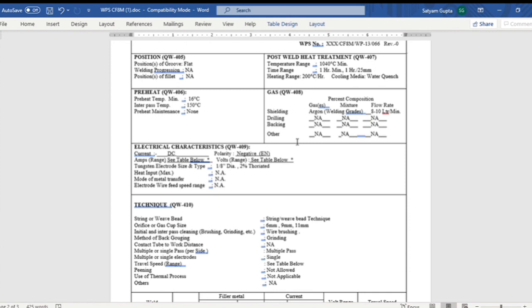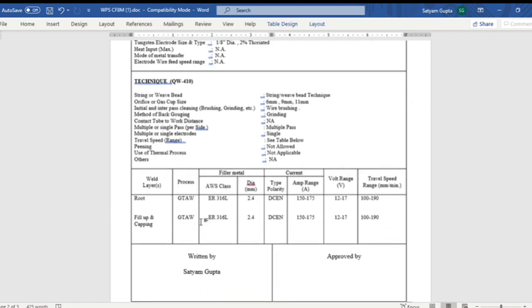Now you need to refer to the electrical characteristics, QW409. You can see the current is DC, polarity is negative. So you can use this current and polarity for this WPS. You can also see the tungsten electrode size and type, 1/8 dia, 2% thoriated. QW410 defines the techniques: string or weave bead, orifice and cup dia, initial and interpass cleaning by wire brushing, method of back gouging by grinding, multiple or single pass is multiple pass, multiple or single electrode is a single electrode.